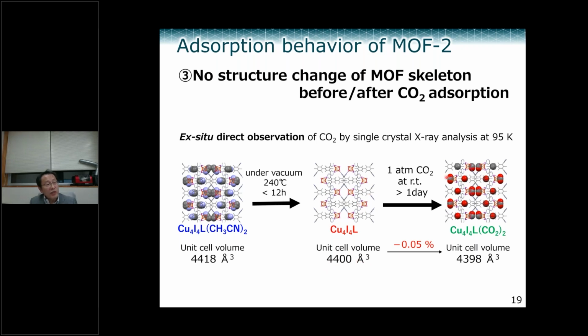Then we introduced CO₂ at room temperature over 1 day. As we expected, we could see a CO₂ molecule in a void like this. Each void contained one CO₂ molecule, as expected from the sorption measurement. In this case, the cell volume is slightly smaller, just 2 cubic angstrom smaller than this one. So the volume change is almost negligible; you can say almost no volume change occurred.